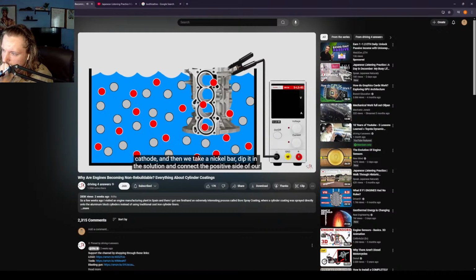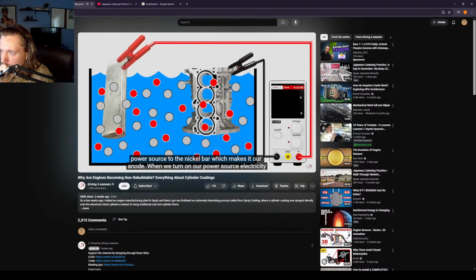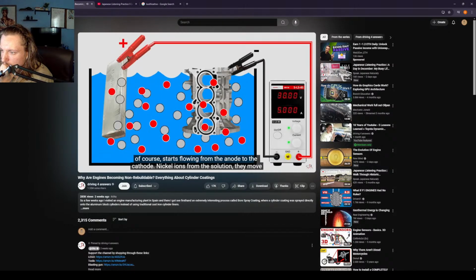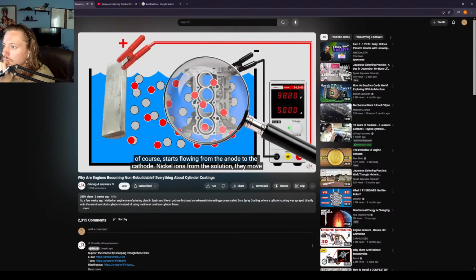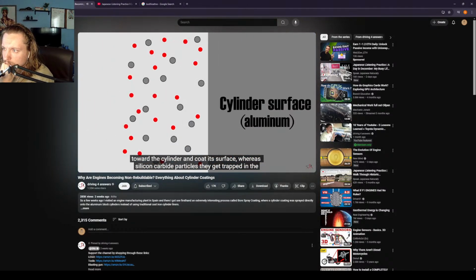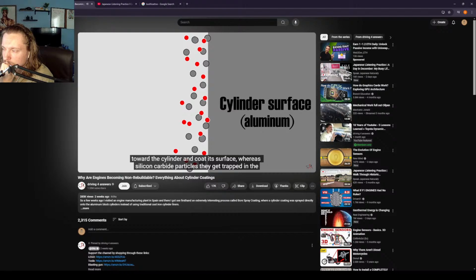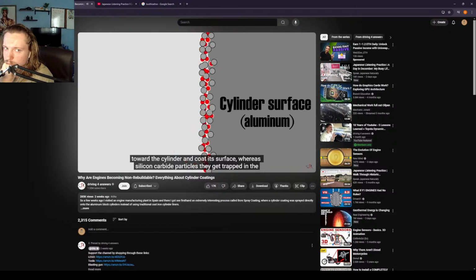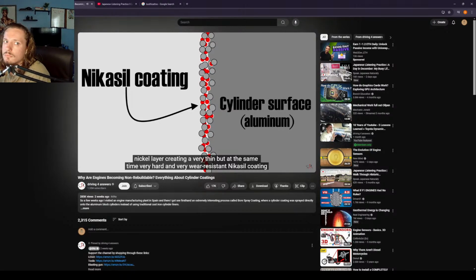And then we take a nickel bar, dip it in the solution, and connect the positive side of our power source to the nickel bar, which makes it our anode. When we turn on our power source, electricity of course starts flowing from the anode to the cathode. Nickel ions from the solution, they move toward the cylinder and coat its surface, whereas silicon carbide particles, they get trapped in the nickel layer, creating a very thin, but at the same time very hard and very wear-resistant Nikasil coating.